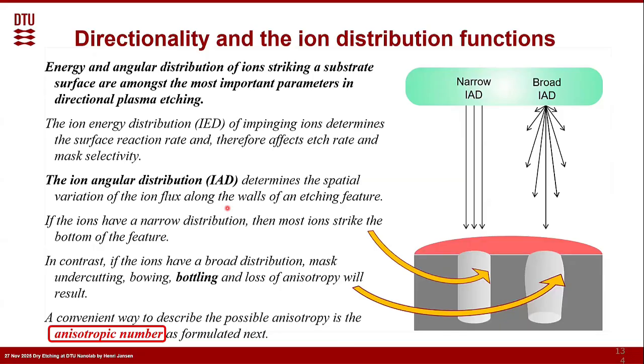And now we're going to talk, before we come close to a break, about the directionality. And that means including the ion distribution function. The energy and angular distribution of ions striking a substrate surface are really among the most important parameters in directional plasma etching. The ion energy distribution, or IED, of impinging ions determines the surface reaction rate and therefore affects etch rate and mask selectivity. The ion angular distribution, the IAD,